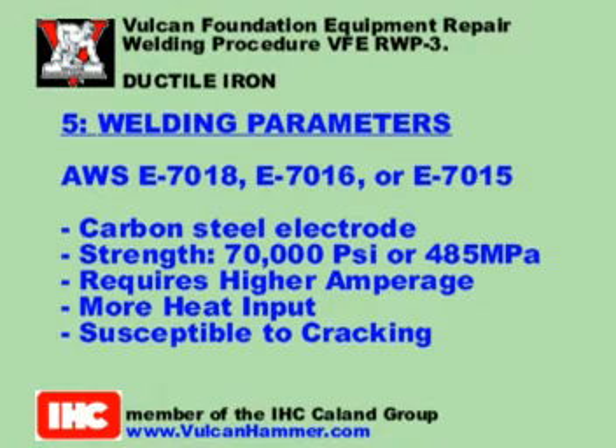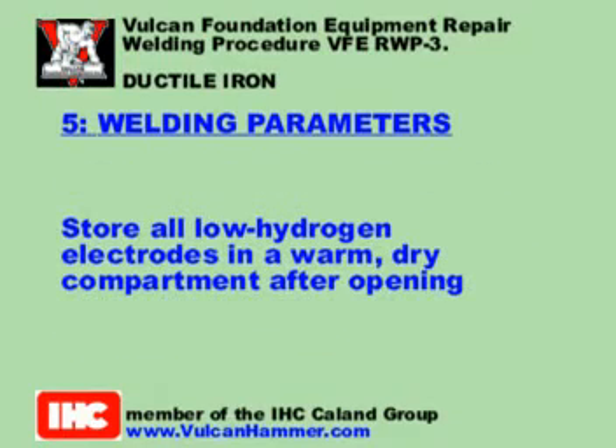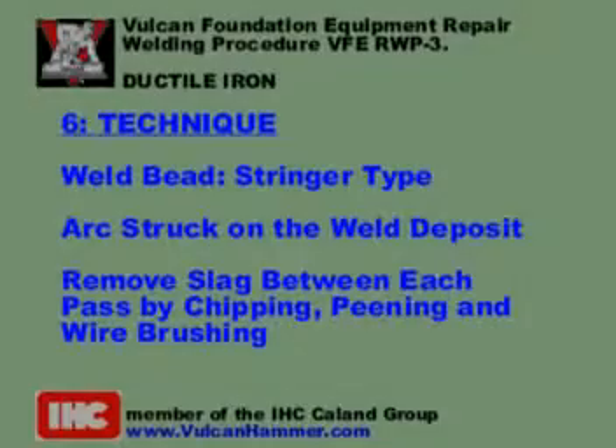Option 2. AWS E7018, E7016, or E7015. This is a carbon steel electrode with a higher strength as deposited, 70,000 psi or 485 MPa minimum tensile. It requires a higher amperage, more heat input, and is more susceptible to cracking. As with all low hydrogen electrodes, they should be stored in a warm, dry compartment after the cans are opened.